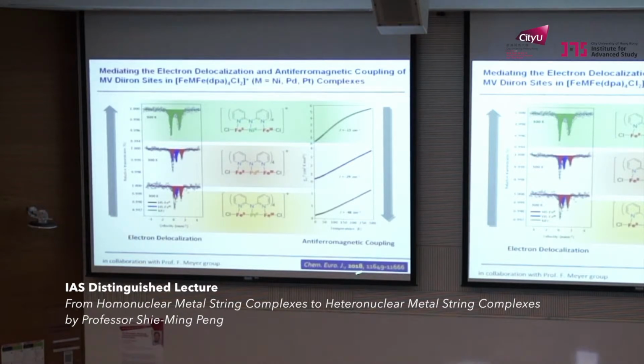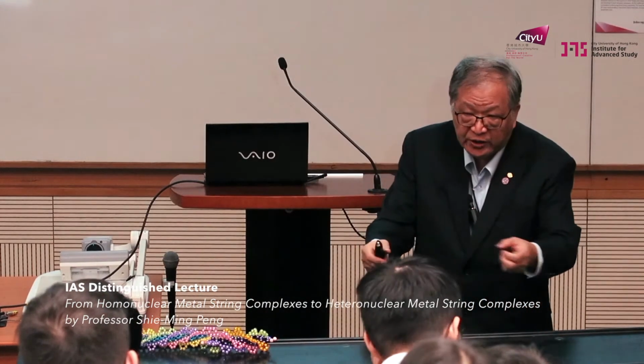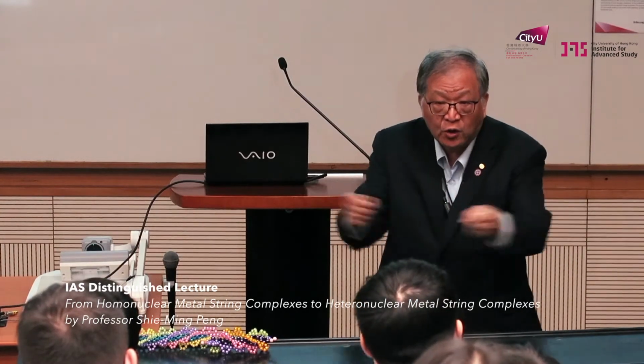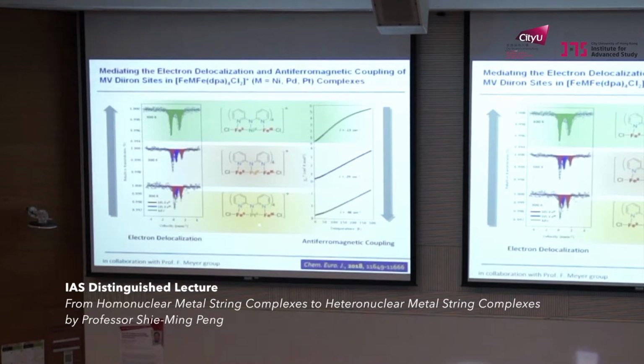And this series we just published this year, we got compounds iron 2, nickel 2, iron 2, and mixed valence iron 2, iron 3, and also the oxidized species iron 3, iron 3. The most interesting thing is that in the mixed valence unit, iron 2 and iron 3, different D8 metals will mediate their interaction. When the central ion is nickel 2, the iron 2, iron 3 is delocalized from the Mössbauer spectrum. You cannot differentiate which one is iron 2, which one is iron 3. They are delocalized. But when you change from nickel 2 to palladium 2 or platinum 2, then this mixed valence becomes localized. Mössbauer shows you that they have iron 2, iron 3, iron 2, iron 3. So the central ion can play an important role to mediate the communication in the mixed valence one.